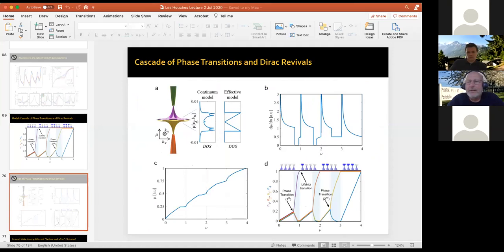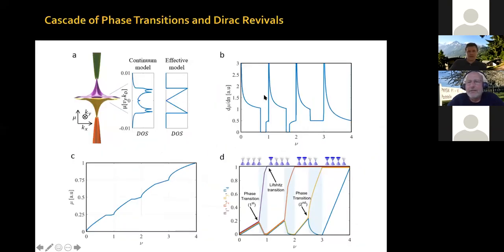Yes. These fillings. So this mechanism, our theory colleagues at the Weizmann Institute have actually calculated this, okay? So the system really wants to do that. If you take a simple effective model for the band structure of these flat bands of graphene, you basically have Dirac cones and then the band ends. More realistic models are different, but you can capture the essence with the simple band model for the flat bands of graphene, and you introduce now Coulomb interactions. There is a critical minimum interaction strength that is needed, but if you are above that minimum interaction strength,